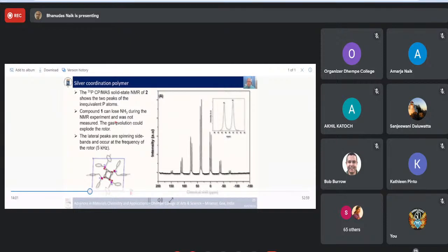And unfortunately, we couldn't do the solid state NMR of 1 because 1 loses ammonia quite easily. It's in equilibrium, so you go back to the acid. And if you have gas evolution in the sealed rotor, it can explode. You have a lot of energy involved in the rotation, so you put a lot of energy into your compound, and this will cause the ammonia to leave.